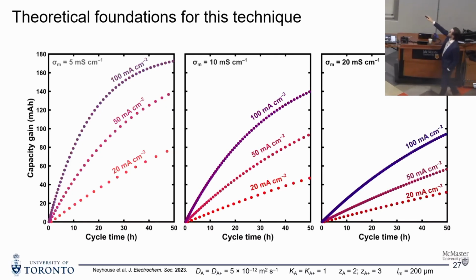But what we see as we look at the capacity gain, not only is our capacity gain a function of conductivity, so a function of one of our key transport properties for our membrane, but it also is clearly a function of current density. So this effectively shows that change as we increase the strength of the electric field, the rate at which we're moving ions affects the rate at which that crossover is happening, and we can measure that via the capacity gain of the cell. And it corresponds to both conductivity, and I'm showing this for a fixed permeability or a fixed diffusion coefficient, but it also changes with increasing diffusivity and crossover rate.